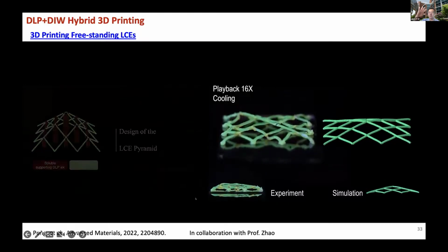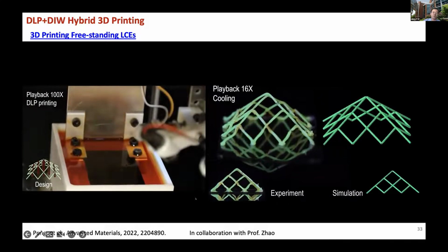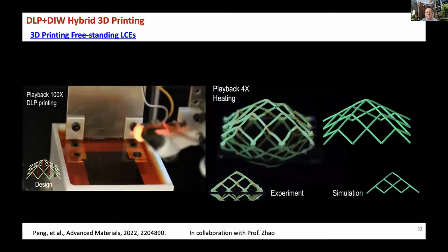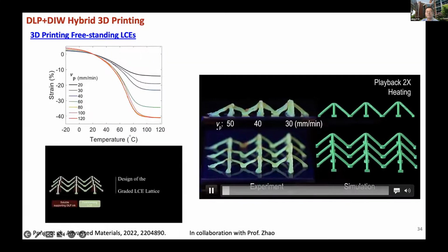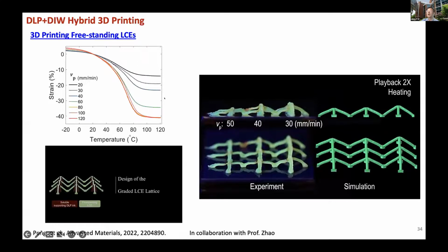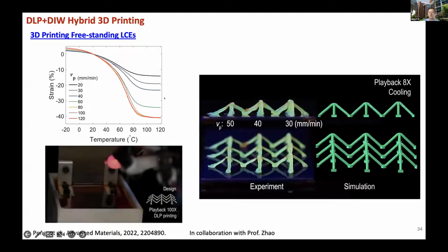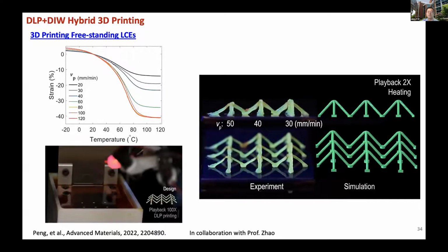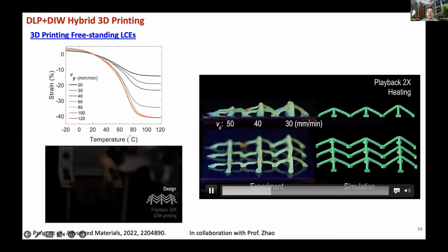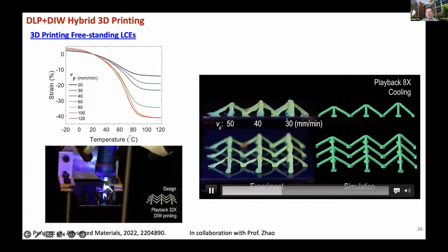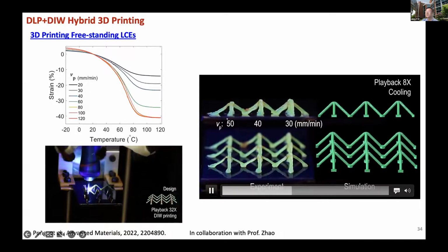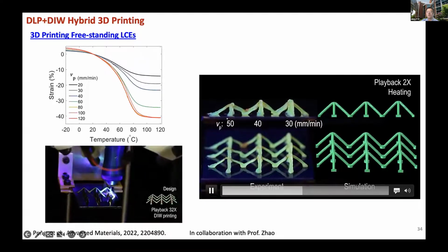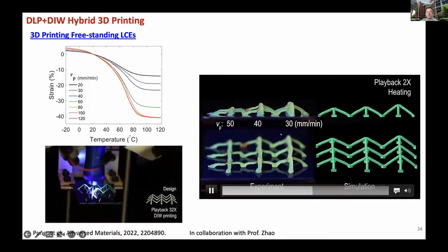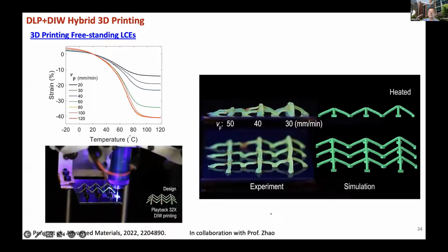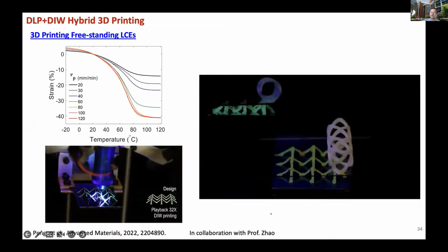When you heat it up, it just comes down. When you cool it down, it just comes back. You can do this repeatedly. We can certainly create some kind of functional structure. Like I said before, the actuation of LC also depends on your printing speed, right? So in this case, we're using higher printing speed on this side, lower printing speed on this side. So this side will give you a higher amount of actuation. This one gives you a lower amount of actuation. So we can actually create a lattice that has a kind of gradient of actuation.